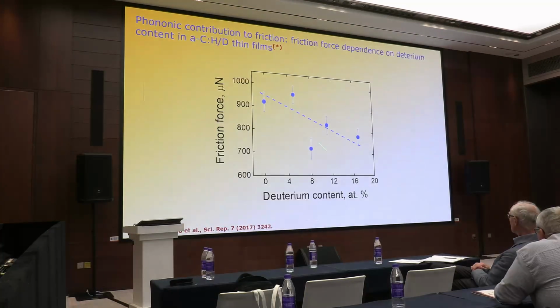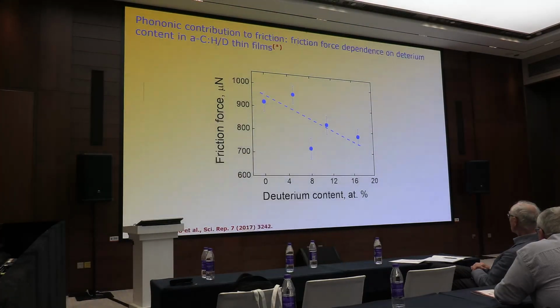Okay, and these are the experimental results. You can see that there is dispersion, but we repeated many times, maybe 10 times. It's too much, but okay, the point is there. But the behavior is clear. The friction force decreases with the deuterium content. With more deuterium content, we have a lower friction force or a lower friction coefficient.